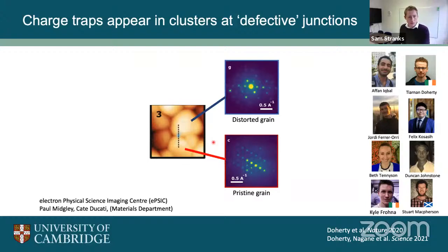We can also use electron microscopy techniques to understand why they trap in certain regions. And this is some work we've been doing where we can identify these traps, so these losses. On the left here is an image looking at these grains, and there's that little blue spot you can see at the center here. That's a trap state that we can identify using these techniques.